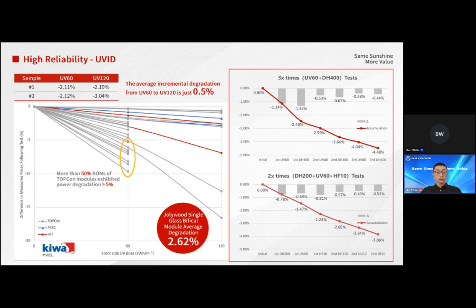UV resistance is another key factor when evaluating the durability of TOPCon modules. According to the brief summary of the PVEL 2024 scorecard, more than 50% of the TOPCon modules tested exhibit power degradation greater than 5% after just UV60 testing. However, the Jolywood module has shown significantly better results after UV120 testing. The average power degradation across two sample modules was only 2.62%. And the degradation from UV60 to UV120 was only an additional 0.5%, which highlights the outstanding UV resistance of the Jolywood modules.